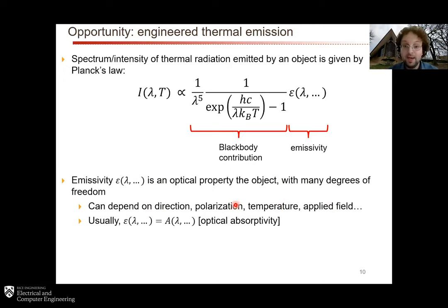and so forth. And a very famous result that's easily derived from basic thermodynamic considerations is Kirchhoff's law of thermal radiation, which states that the emissivity is exactly equivalent, for objects that are reciprocal and in equilibrium, to optical absorptivity, which means that if you know how to engineer optical absorption, for example, by nanostructuring, by having plasmonic resonators, by having dielectric thin films, and so forth, if you can engineer this optical absorptivity, you can also engineer the emissivity. And that's very, very useful.